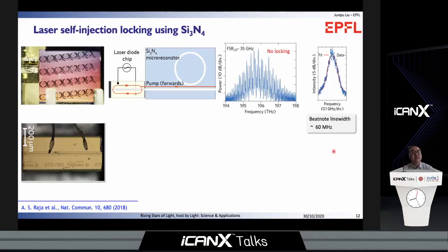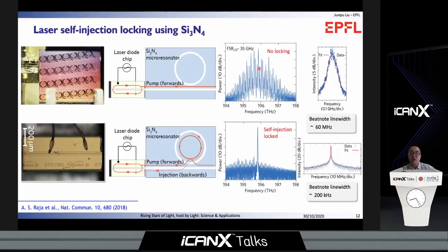We also perform this with our silicon nitride device. In this case, we use an indium phosphide laser diode, which is butt coupled to our silicon nitride chip. Initially, the laser diode has multimode lasing, and the laser linewidth is broad. By changing the current to the laser diode until one mode coincides with the resonance of the microresonator, the light is coupled into the resonator and triggers laser self-injection locking. Therefore, the multimode laser diode becomes a single mode laser, and the linewidth also gets reduced significantly.